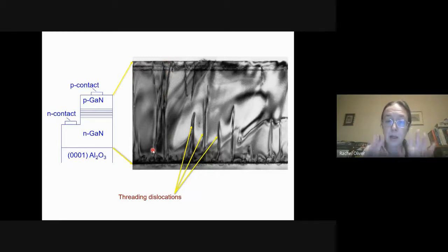I said we were looking at a line end on. Now we're looking at the same lines from the side, and we can see that they penetrate all the way through the device. The reason they're present is that we're growing our gallium nitride on a substrate which is a different material, in this case sapphire, and that leads to stresses and strains which lead to the generation of dislocations.